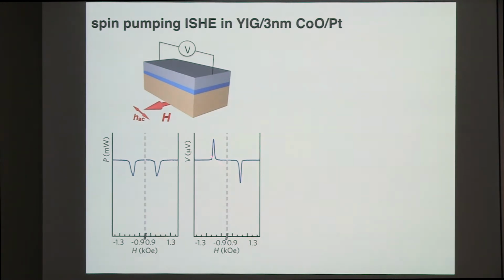So here is a very common spin pumping data at 150 Kelvin. We have the microwave absorption at the FMR point, and the corresponding inverse spin Hall effect. When you see this, you know that you already have spin injection due to FMR.